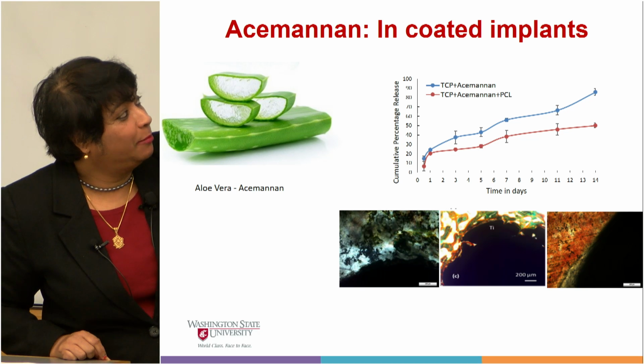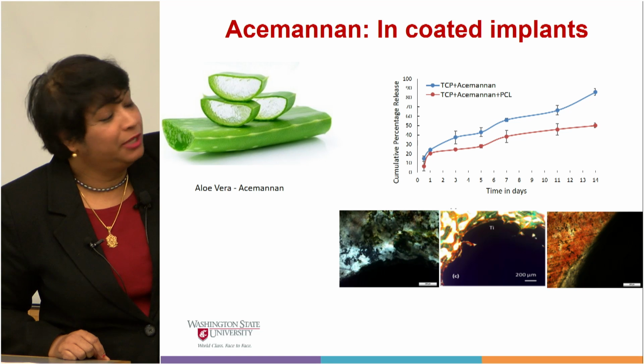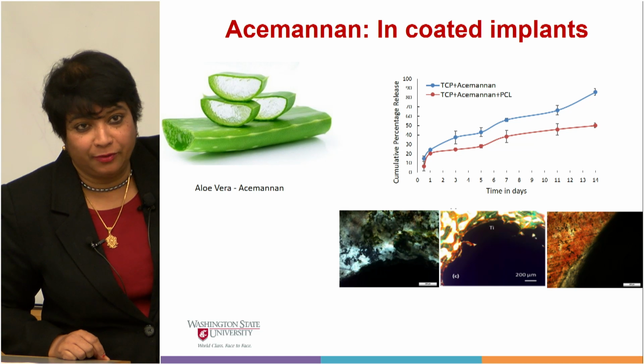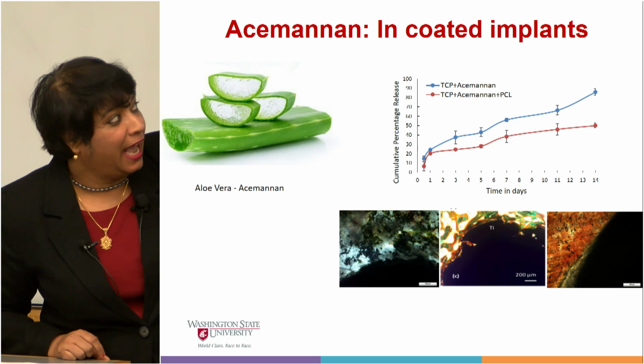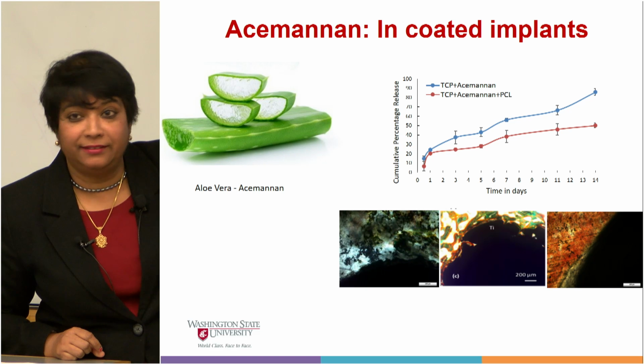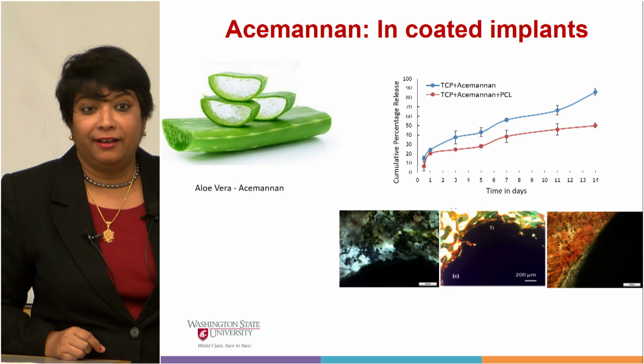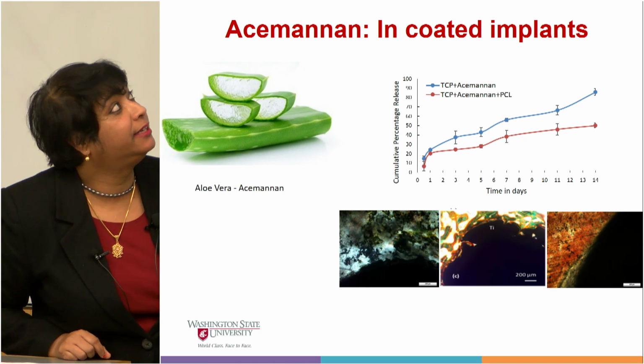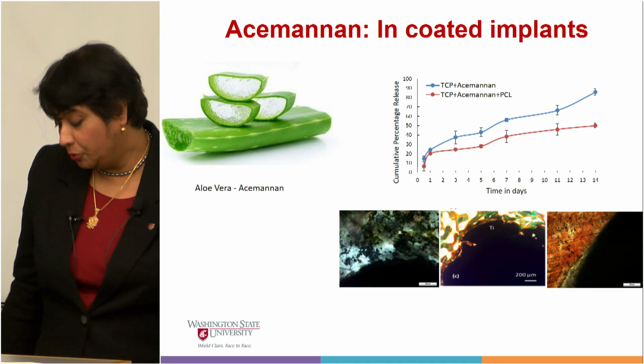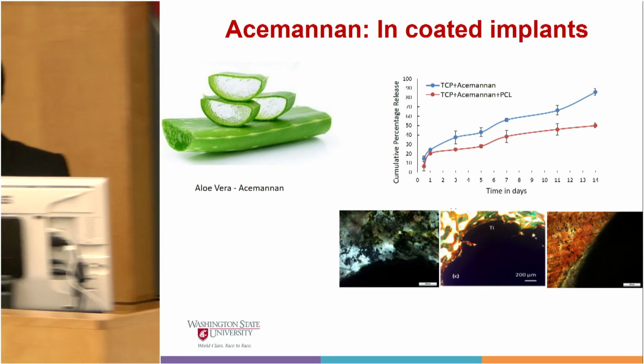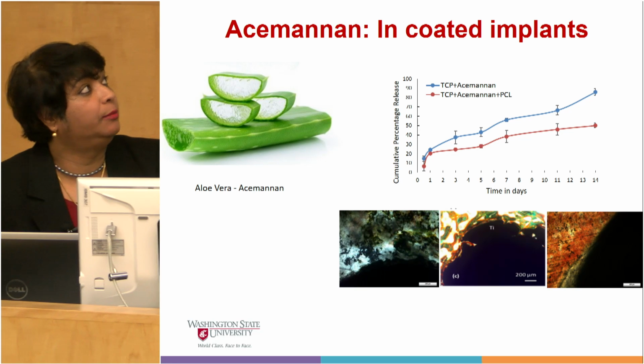So porous titanium, black is the metal. In between is hydroxyapatite, which is a calcium phosphate, bone-like material. And the extreme right one is the image with aloe vera in rat distal femur model. We have also shown that we can control release kinetics using polymer.